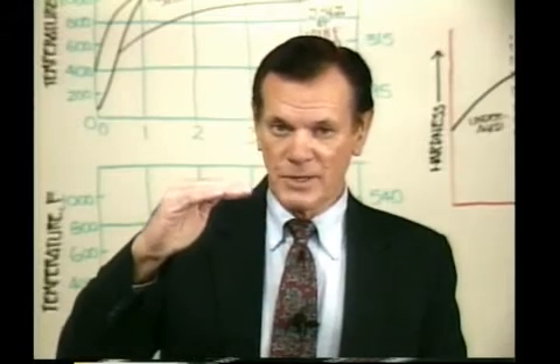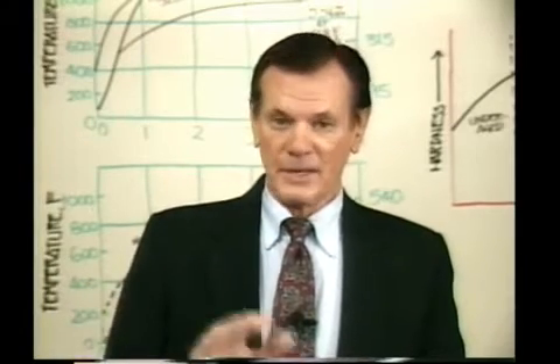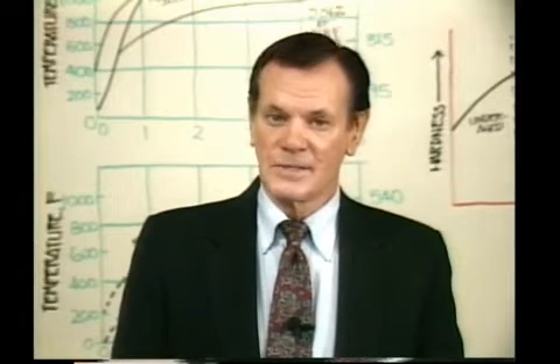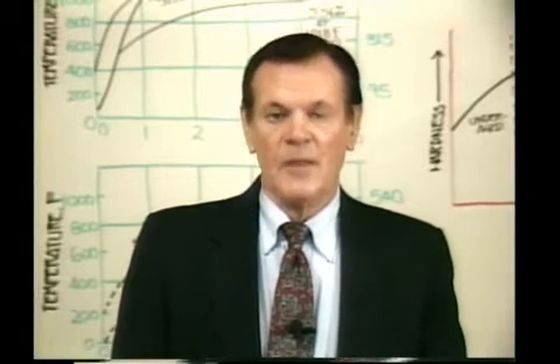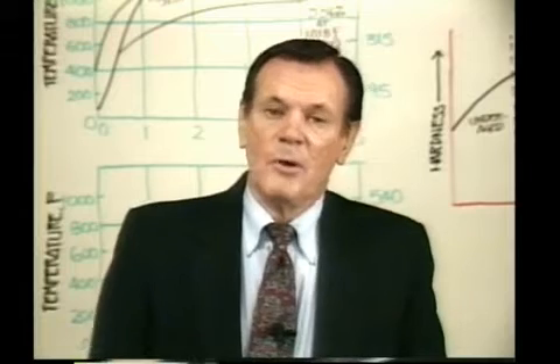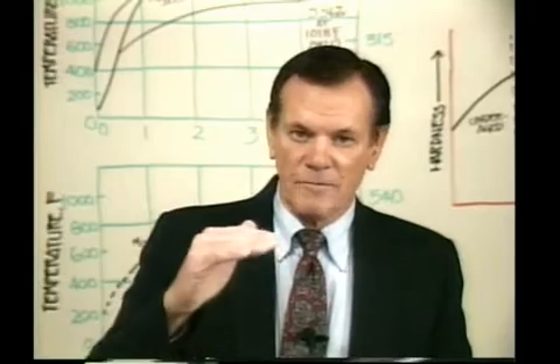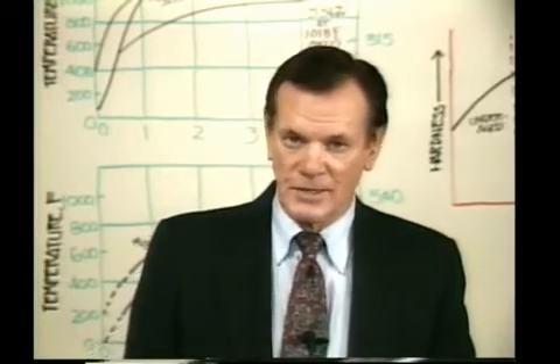The rate at which the hardening elements dissolve in aluminum alloys in the solid state increases greatly with increasing temperature. For instance, very little copper will dissolve in the aluminum in the solid state at room temperature, while at 900 degrees, approximately 5.6% copper will dissolve. The final tensile and yield strengths of heat-treatable aluminum alloys are directly dependent upon the amount of hardening atoms that are dissolved before quenching. Most high-strength 2000 and 7000 series aluminum alloys show the highest level of properties at the highest solution heat treat temperature.